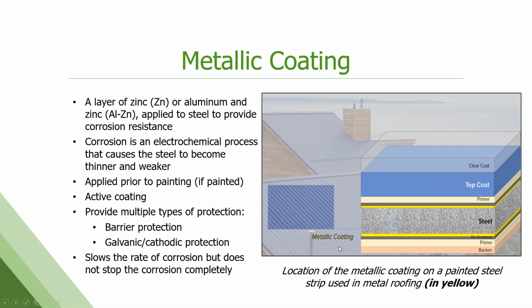I have a little cross section here of what a factory painted steel product would look like. The steel in the middle is by far the majority of that total thickness. You would then have your layer of metallic coating, which would be the yellow on here. And then if it's painted, you'd have a little bit of pre-treatment, and then primer, and then your top coat and your backer paint. So again, the metallic coating is very, very thin in relation to the rest of it, but provides a lot of protection and performance characteristics.